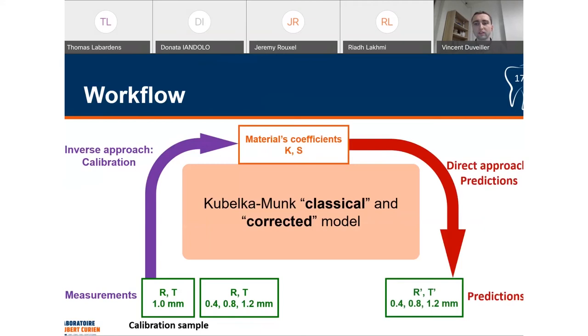We do not predict the reflectance and transmittance for 1 millimeter because, as the equations of the model are reciprocal, the predictions are equal to the measurements, so it's not interesting. Once we get these predictions, we can compare them with the measurements using the CIE delta 2000 color distance metric. This metric gives the distance between two spectra in the LAB color space.